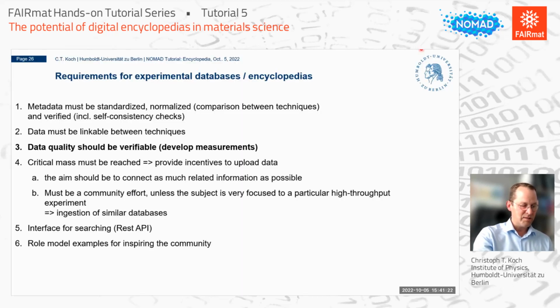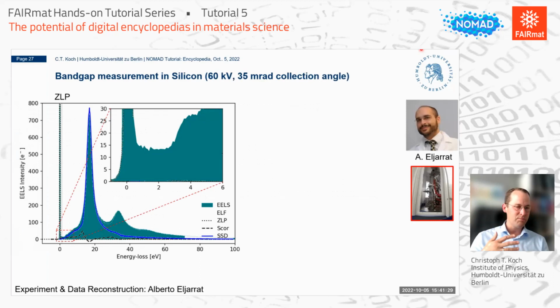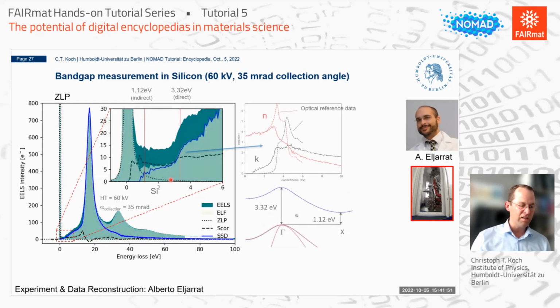Right, and the next point: data quality should be verifiable. I just want to give you one example, and I know this is again specific to the field that I work in. This is an electron energy loss spectrum of silicon, where there is some band structure information hidden. The band gap is in this regime here. There's a direct and an indirect band gap between 1 and 3 eV. The direct band gap is at 3.3 eV and the indirect one at 1.1 eV.